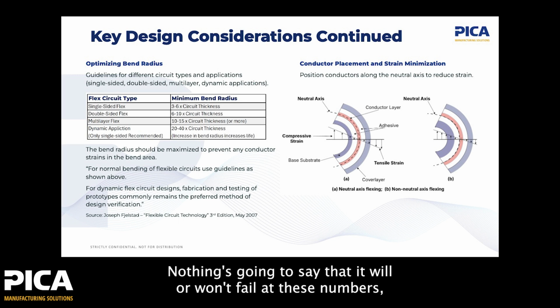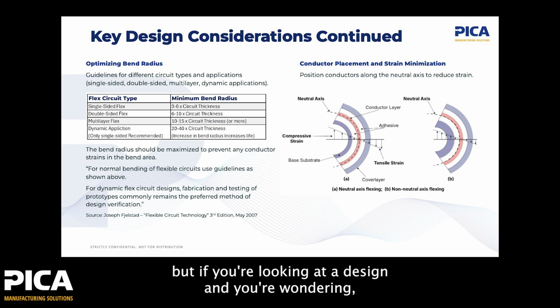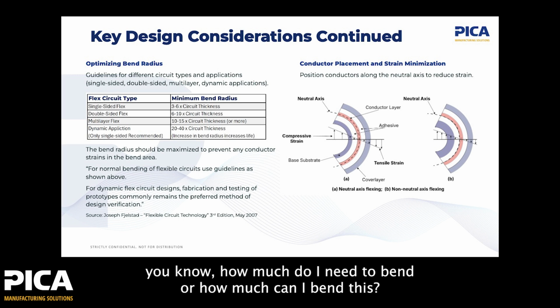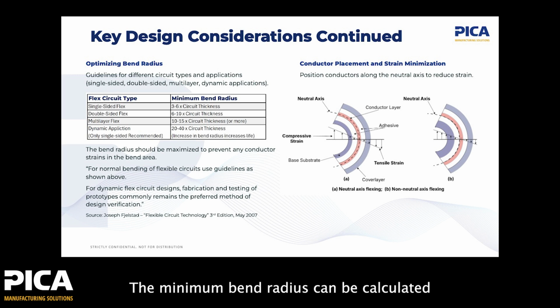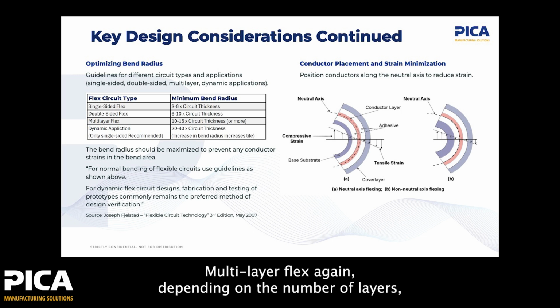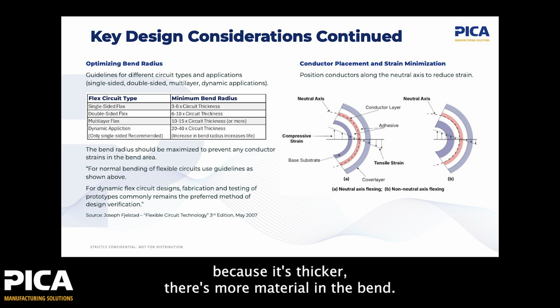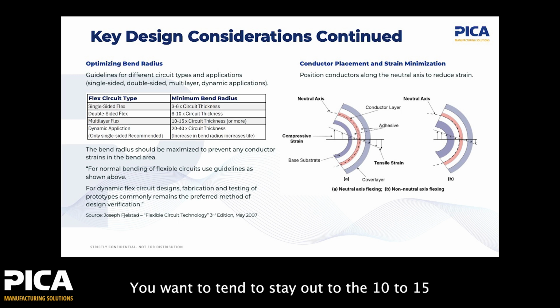Nothing's going to say that it will or won't fail at these numbers, but if you're looking at a design and you're wondering, how much do I need to bend or how much can I bend this, the minimum bend radius can be calculated in this way. Multilayer flex, again, depending on the number of layers, because it's thicker, there's more material in the bend, you want to tend to stay out to the 10 to 15 times the thickness. And again, these are just general rules of thumb.